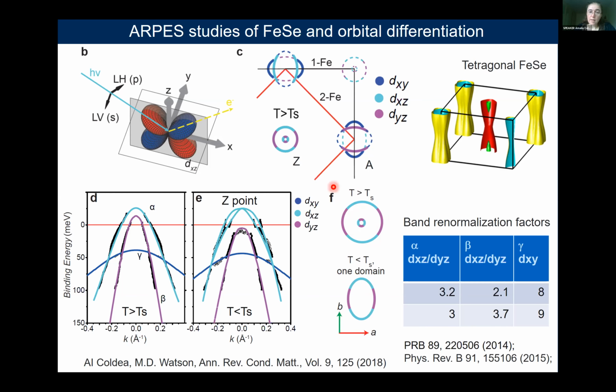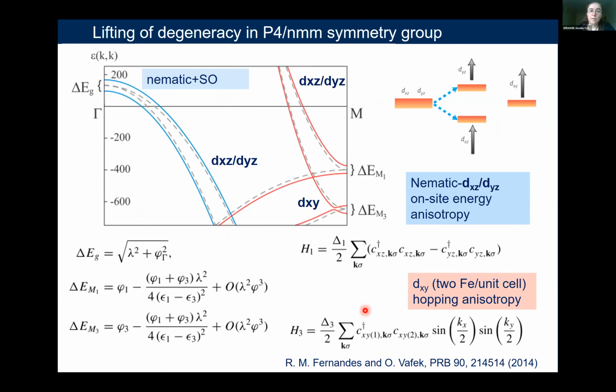temperature. So these are the generic aspects that one would expect to happen inside the nematic phase, and this is exactly how we expect the nematicity to manifest as a direct elongation of the Fermi surface and consequently affecting the transport and potentially developing anisotropic scattering in this configuration.